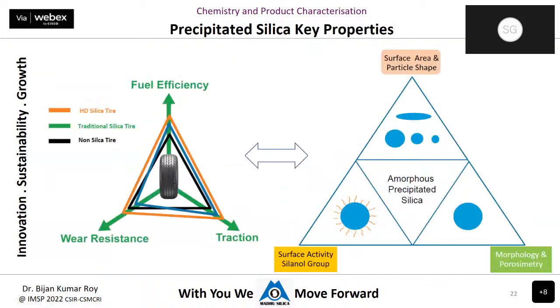Now in a tire, these are the 3 important parameters one needs to achieve, otherwise a tire cannot run in the field. One is fuel efficiency, another is wear resistance, and the third is traction. Traction means your safety. Fuel efficiency means rolling resistance should be low, and good wear resistance means the tire should be durable. It should run for a longer period, say 50,000 kilometers, even 1 lakh kilometers. So these are the 3 major properties required of a tire, and these can be translated for silica, to control by means of surface area, particle size, surface activity, or the morphology and porosity.